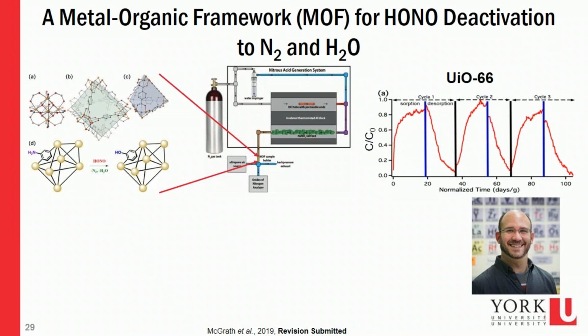So what we do is we produce a known quantity of HONO using a typical HONO generation system, doing acid displacement of sodium nitrite with hydrochloric acid. We then take a very tiny sample of MOF. We put it in a 1/4-inch tube. It's like this long. Sometimes we put a whole gram in there, and then we expose it to HONO for long periods of time. We measure it, again, using a modified nitrogen oxide analyzer to look at the HONO that's getting through that MOF as a function of time.